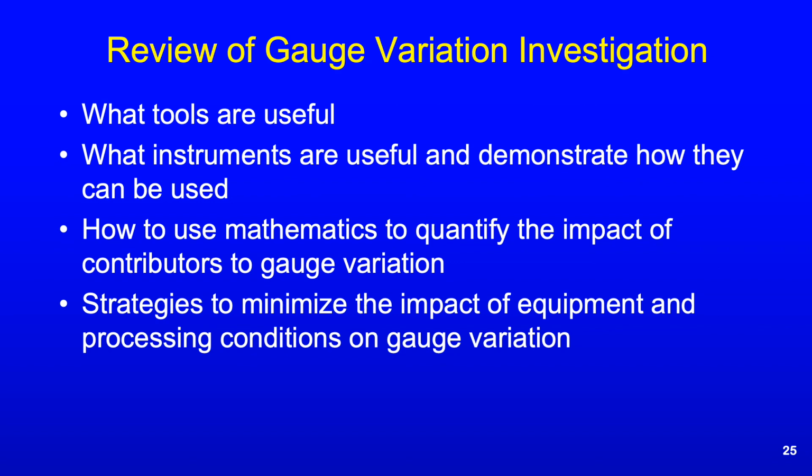The capacitance gauge profiler was able to identify the fact that there is a very high concentration of pigment where there shouldn't be, and that was a clear indication of port lines. The film was so thick that you wouldn't have known because they weren't going to be tearing the film. It was really 3.5 mil. It's pretty tough stuff.